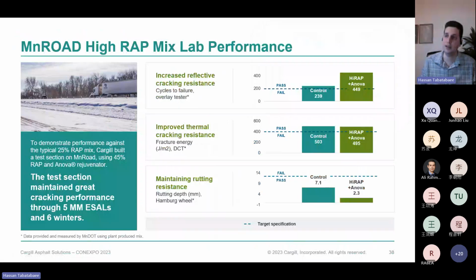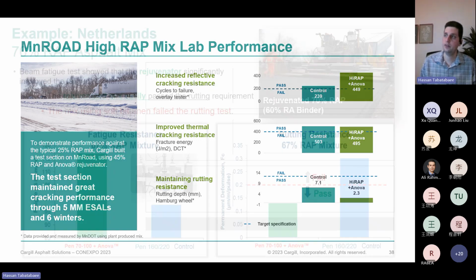This is a 4-lane highway, a 3-lane highway on either side. And after 6 winters, including one of the record coldest winters in Minnesota, which is one of the coldest states in the US, there has still been no need for maintenance on this road, which generally has to happen because there's a lot of transverse cracks that open up very widely. So definitely, there's no need to sacrifice pavement performance, as shown in these two test sections with high RAP content. Here's an example of 70% RAP in Netherlands.